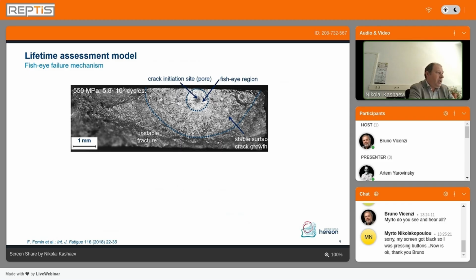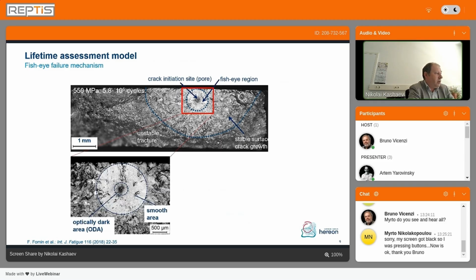And then if we look at the fracture surface in this observation at higher magnification, we see that we have a rough area around the pore. It's known as an optical dark area, and after that we have a smooth area where we have more plastic deformation during the fatigue crack growth.